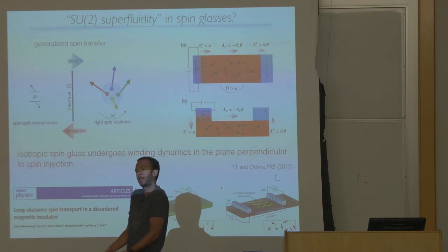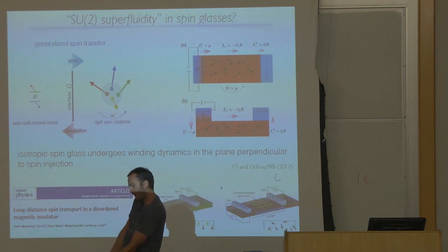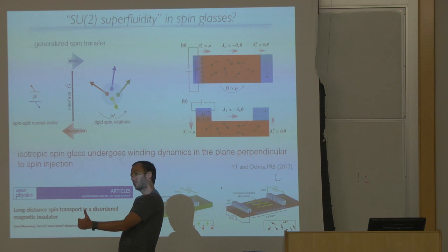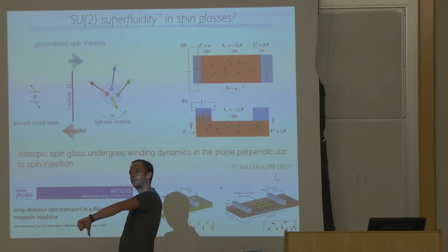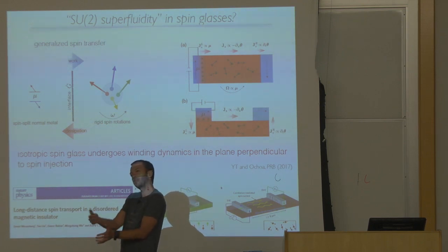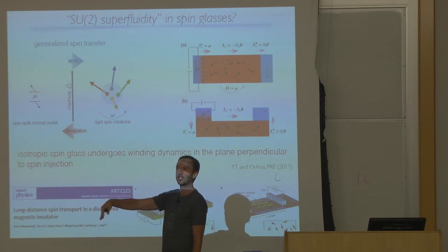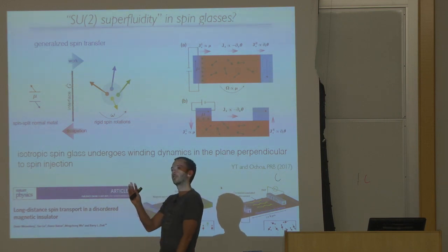There is an energy barrier for the phase slip. There's some easy-plane anisotropy, and the phase slip is accomplished by magnetization coming out of the plane and crossing a north or south pole. That creates a finite-sized solitonic object that has an energy. You could calculate that energy; it's basically determined by something like the square root of the stiffness, the rigidity, times the out-of-plane anisotropy.